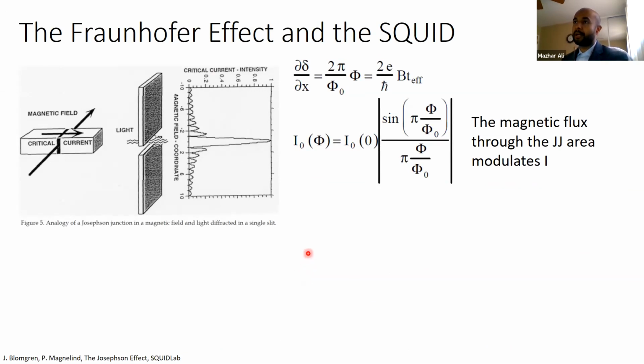Now, there's a couple other important effects to remember. The first, the smoking gun of having a Josephson junction, is the current versus phase relation. Like we said, the current is dependent on the phase difference between the two superconductors, and the phase difference can be modulated by the magnetic field. So through substitution, you can measure the critical current as modulated by the magnetic field, and it takes on this form, which is exactly the single slit diffraction form. And so it actually looks like that.